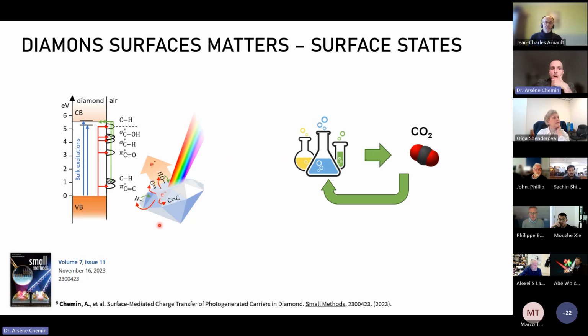The surface states also have a huge impact on the photoexcitation of the diamond because, as I said, they will behave like molecular states. So you can think about the surface state of diamond as small molecules having occupied and unoccupied orbitals at the interface. And thanks to X-ray spectroscopy, actually, we were able to completely map the position of the surface states with CH, sp2, CO, CH, etc., within the bandgap.